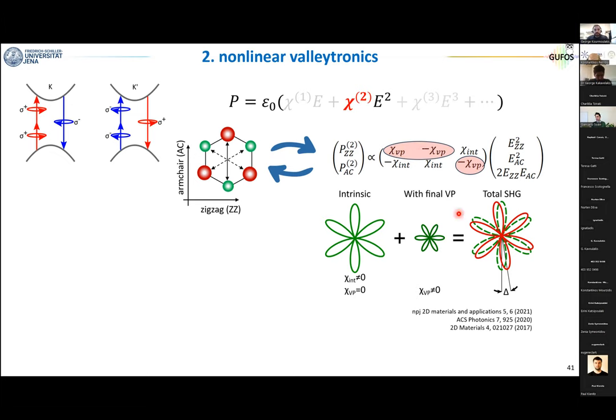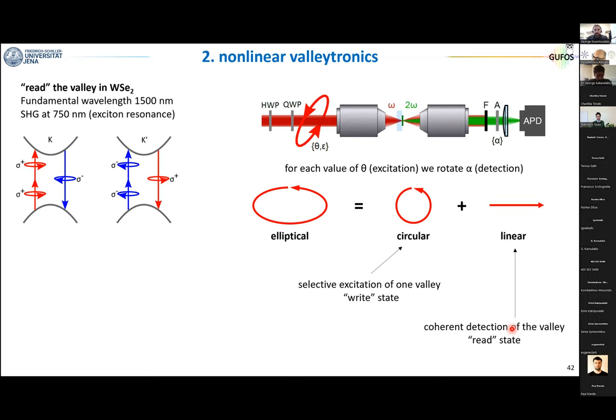Now, from this matrix, you can immediately observe that these valley polarization terms are orthogonal with respect to the intrinsic response. In other words, now there is a new second harmonic element: if you excite the sample along the armchair direction, you emit second harmonic along the zigzag. So orthogonal to the intrinsic response. Overall, this six-fold pattern will be rotated by a certain angle, delta or theta. And this angle is a direct fingerprint of valley imbalance and broken time reversal symmetry. So how do we do this experiment?